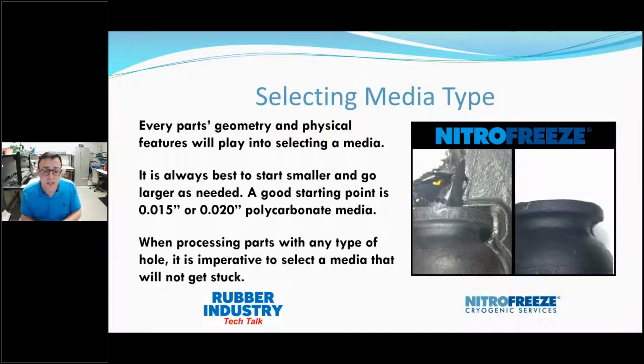We have several machines, and we don't like to always switch out our medias. You can do a machine changeover during the day multiple times, and we always recommend to start with the smallest media and work up in size as we go through the day. So more often than not, we start with a 15 thousandths media, run whatever parts we need to run with that, then move to a 20 thousandths and so on and so forth. That way you can try parts with a 15 thousandths media, and you can also try the same part with a 20 thousandths media. And if you get the same result, well, then other variables come into play, like time.